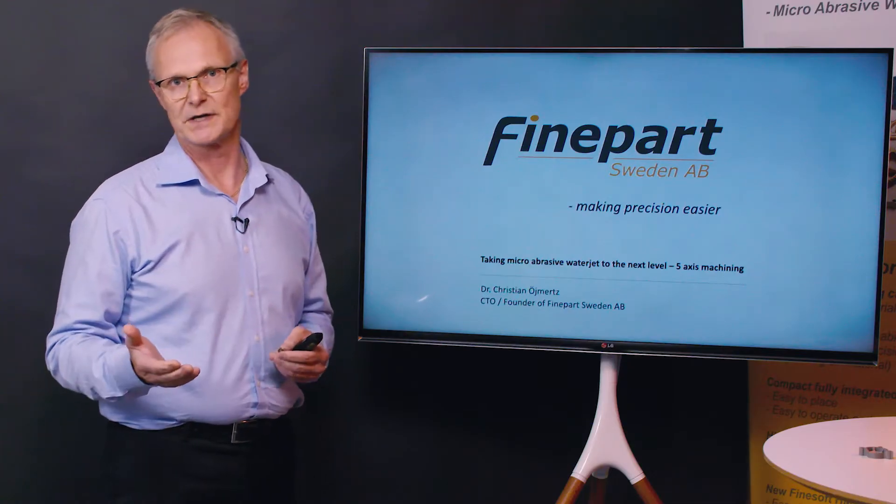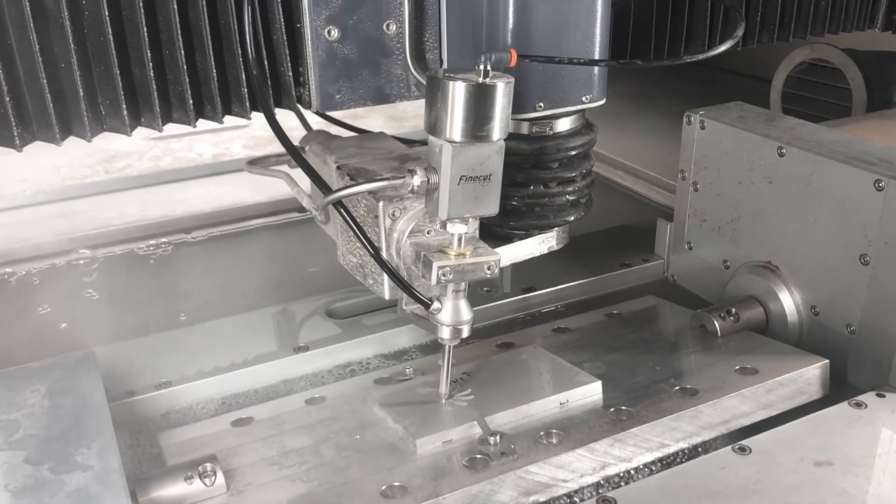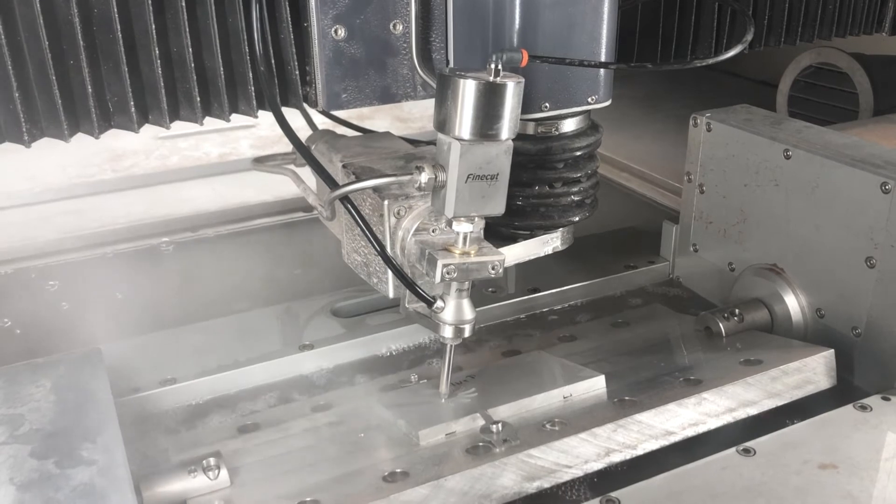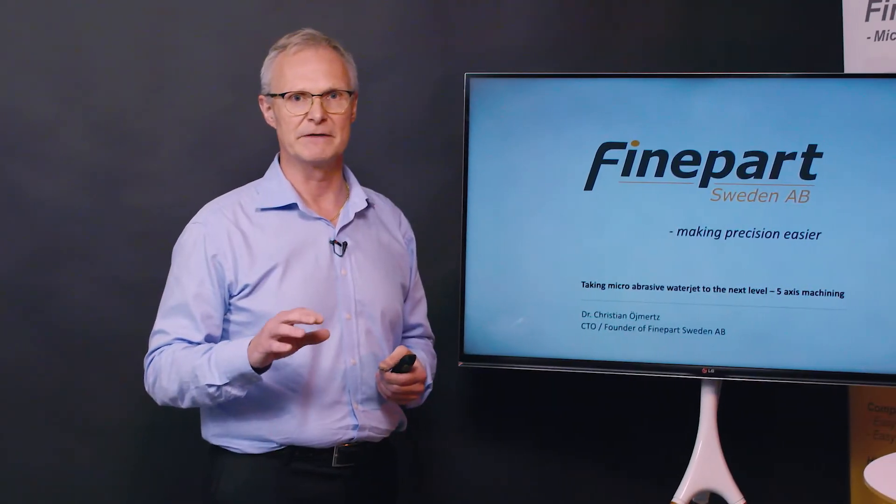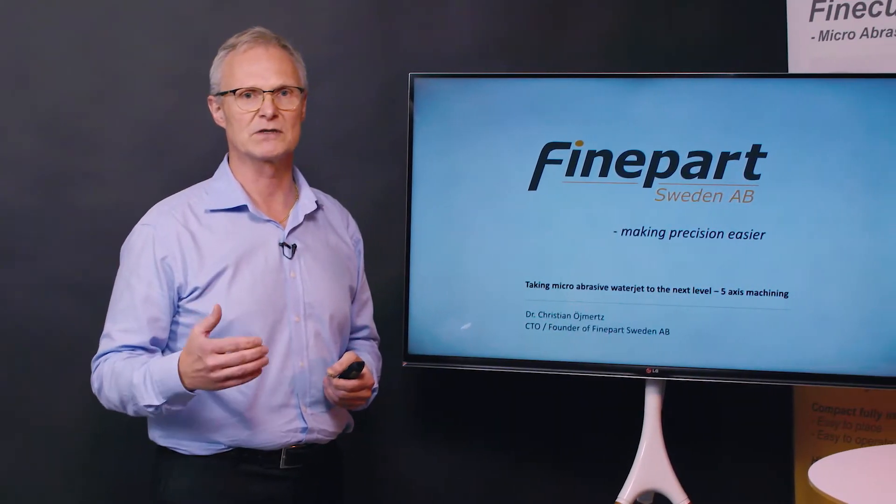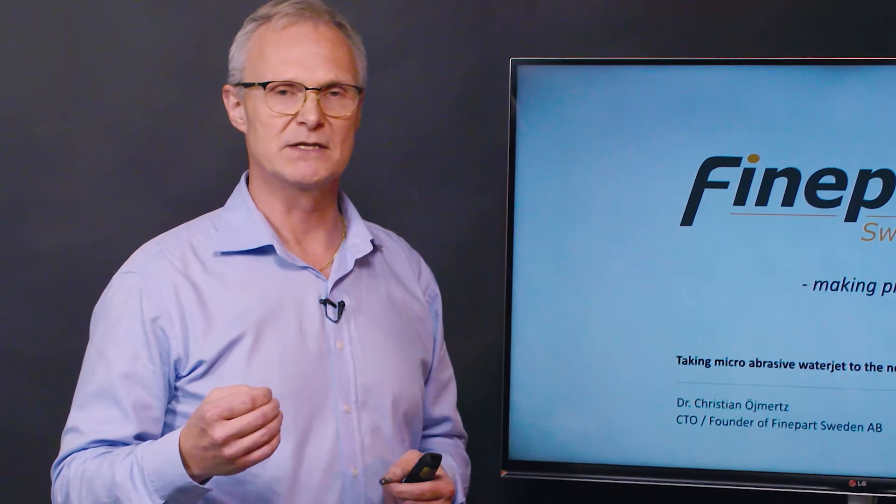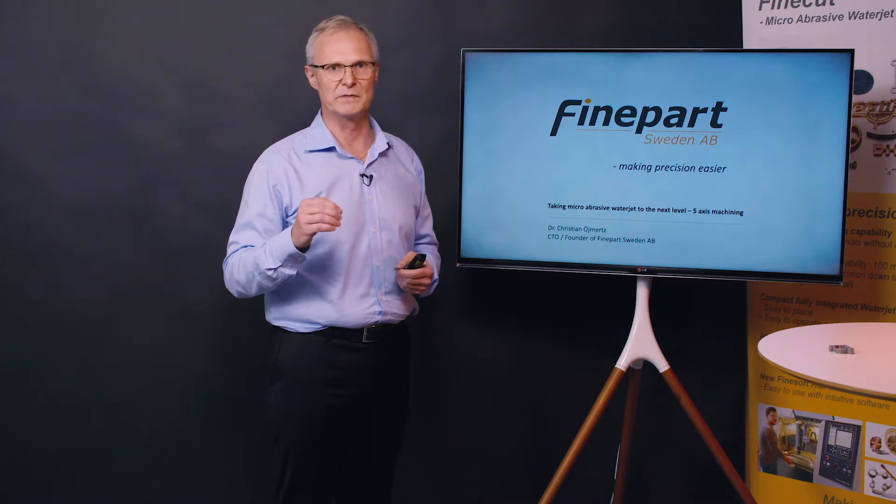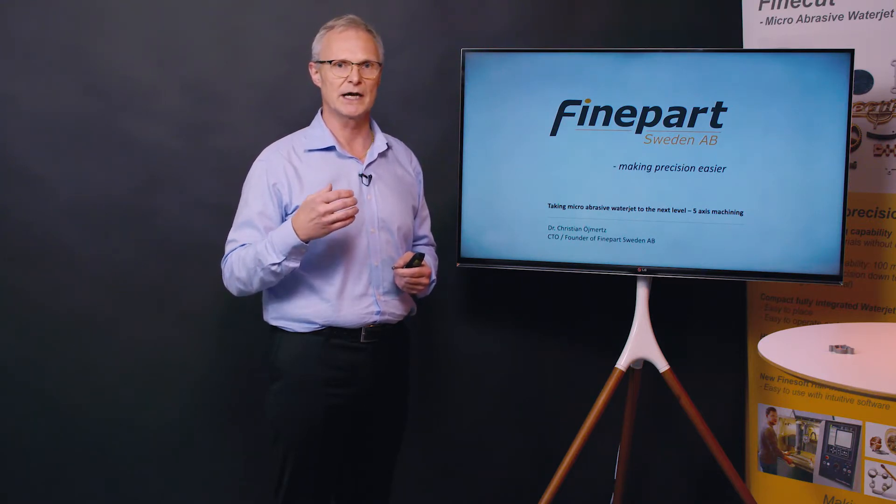As most of you already know the waterjet process has many benefits. Most of all it's a non-thermal process which means that we will not have any thermal effects on the material, no recast layers, no heat affected zones. It's also a process that is based on particle erosion and since the particle erosion can use many different material removal mechanisms the process has the ability to adapt to any type of material.